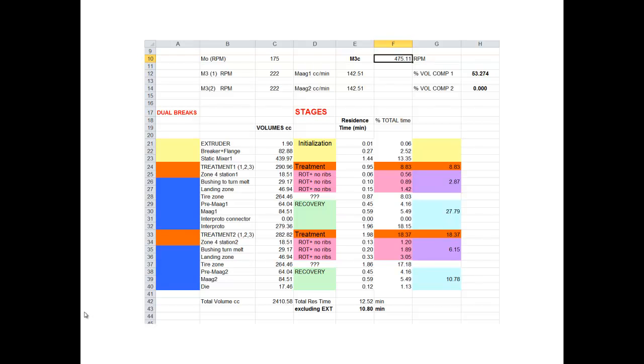And what you see here is, by checking the volumes where the melt flows in, we can determine the residence time, and the total residence time here for this particular melt is about 10 minutes, and it is being treated in the pink zones. Treatment 1, rotation, no ribs, rotation, no ribs, and so forth. Well, in this particular case, no ribs, but in the examples which I will describe, there are ribs. And then you have recovery, another treatment, another recovery, and we see on the column next to it the times for each. So we see that there is some recovery occurring after treatment. The treatment creates rheofluidification conditions at a given temperature, and then there is some recovery, which is the passage of a melt through the end zones to reach the next processor.